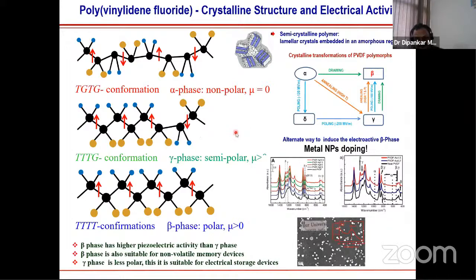So the question comes, how can we reach this particular phase from one phase to another phase? So once we buy it, we have an alpha phase. Then if we draw it, if we give a simple stretching, then we can reach the beta phase. If we apply high temperature, then again we can go to the gamma phase and so on. So this is a very tedious process because one has to stretch it mechanically. Then only one can reach this.